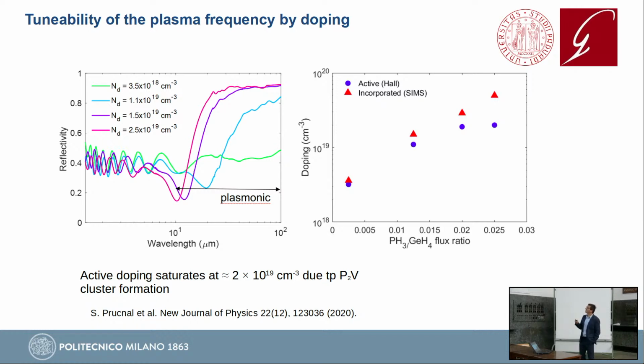And the reason, again, we discovered, thanks to the collaboration with Enrico, comparing Hall effect and secondary ion mass spectrometry. So the Hall effect will tell us the active carriers, so the ones which are really free to move and participate in the plasma frequency, while the SIMS will give us the chemical composition, so how many phosphorus atoms I have in my system. So many of them, we found out, were not in the right place or were not activated. So we have much more phosphorus atoms than electrons in our system.